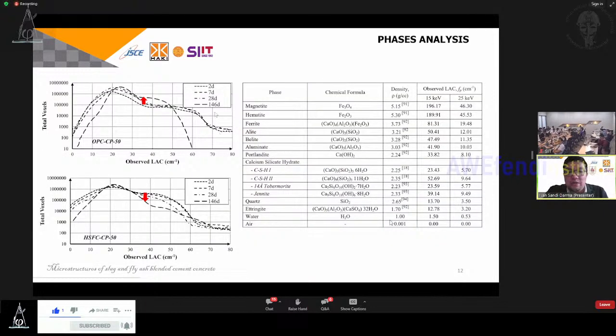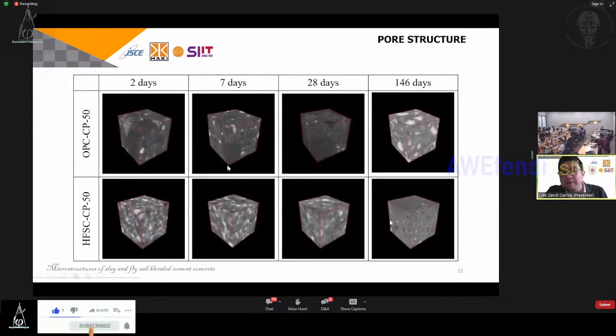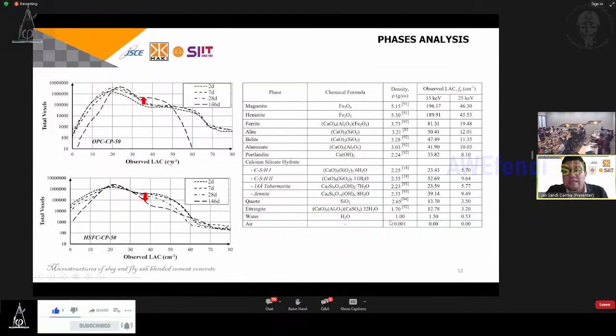And then from this VOI you will have a histogram. From the histogram, you can convert into LAC, linear attenuation coefficient. From the study, we will have the correlation between the LAC and specific items in the microstructure. For example, C-S-H type 1, here we use 15 keV. The value of LAC is around 23.43. And then from here, we could check the change in the microstructure during the curing period.